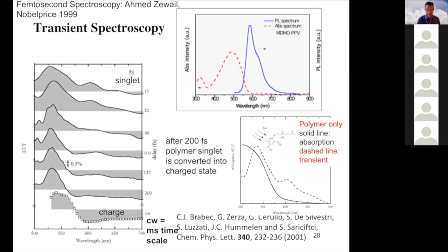So in the beginning, we see something that is very similar to this excited state of the polymer, to the singlet. But as time progresses, that's here, we go from 15 to 30, 60, 100 femtoseconds. So at 200 femtoseconds, the spectrum has changed totally. And now it is basically the same as a spectrum that is taken on a very, very long time scale, a millisecond time scale. And that indicates that you have formed the charges in the film. Within 200 femtoseconds, you have a spectrum that indicates that the charges are formed.